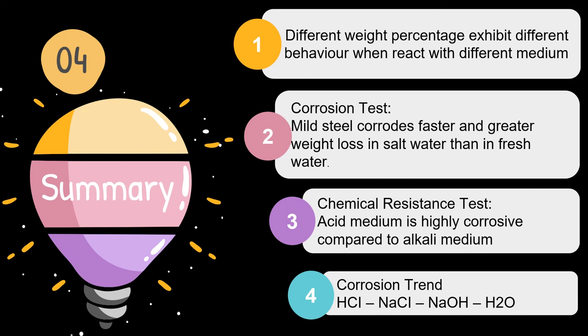Here is the last part to highlight. The different weight percentages of zinc oxide nanopowder exhibit different behavior when reacting with different kinds of media. Based on the corrosion studies, mild steel corrodes faster and experiences greater weight loss in salt water than in fresh water. The chemical resistance test shows that acid medium is highly corrosive compared to alkali medium. Corrosion decreases in the following trend: hydrochloric acid, sodium chloride, sodium hydroxide, and lastly water.